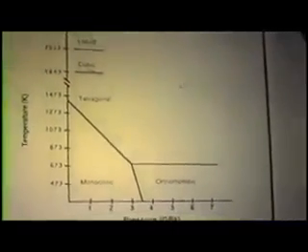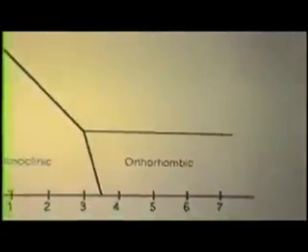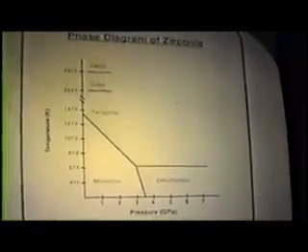Let me return to the structural evolution for a minute because I think there's something interesting here. When you look at the phase diagram of zirconia at atmospheric pressure, the low-temperature stable bulk phase is actually the monoclinic phase. As you took this phase to higher temperature, the transformation happened at around 1450 K into the tetragonal phase. But as I told you already that our materials, as they were heated, transformed first into the tetragonal phase, which often has been referred to as a metastable phase.